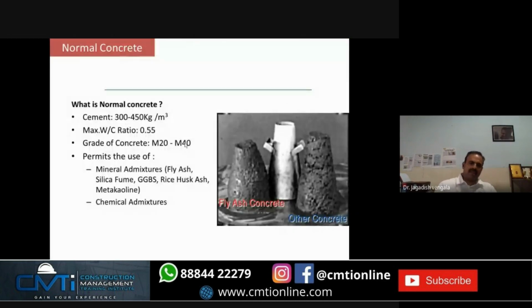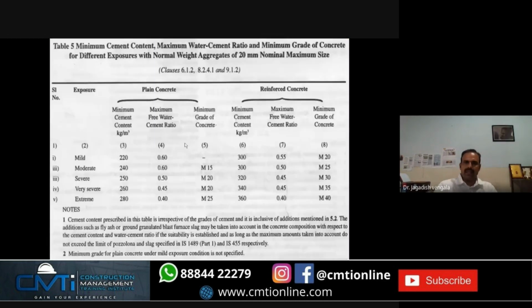So this is a famous table in IS 456. One has to know about it. So we'll concentrate on reinforced concrete. Here you can see, as per IS 456, the minimum cement content you can put in the concrete for reinforced concrete is 300 kg per cubic meter of concrete. Suppose you're making a cubic meter of concrete, the minimum cement content you have to maintain is 300 kg.